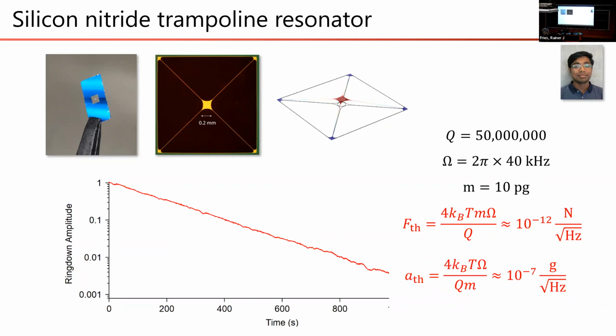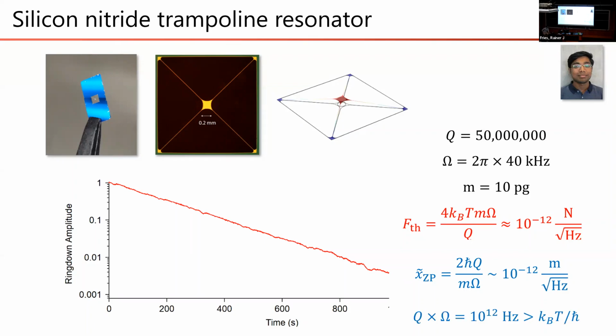Interesting thing about these devices is they're big enough and they're high Q enough that actually they also are interesting as acceleration sensors. Acceleration sensor is a sensor for inertial forces. So in this case, the inertial force is proportional to mass, so you want a larger mass mechanical oscillator. So these devices actually intrinsically have thermal force sensitivities around 100 nanoG at 40 kilohertz, which is not really interesting for many technological applications, but it is interesting for looking for weak inertial forces like might be produced by dark matter. Their zero-point motion, I'm showing the zero-point spectral density, is also quite large, around a picometer, which is eminently accessible without even an optical cavity. And they're quantum coherent at room temperature.